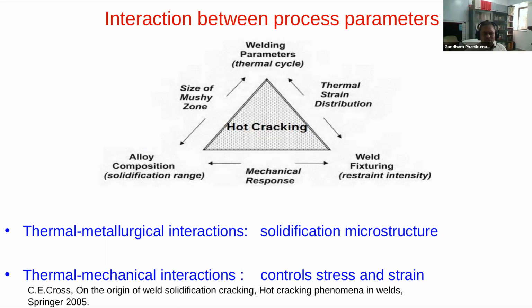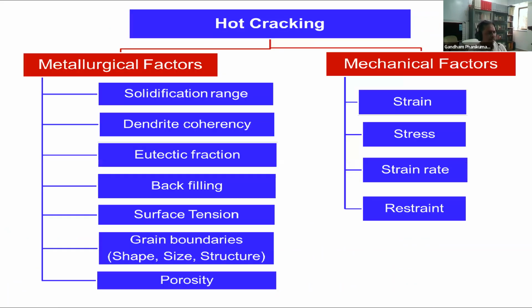Are there examples of alloys which will surely crack if you just try to print them? CMSX4, for example, is a superalloy, and it's a very important alloy. If you don't take care and you print it, sure enough, it will actually crack. So you have to take care of cracks in some highly crack-prone alloys like CMSX4.